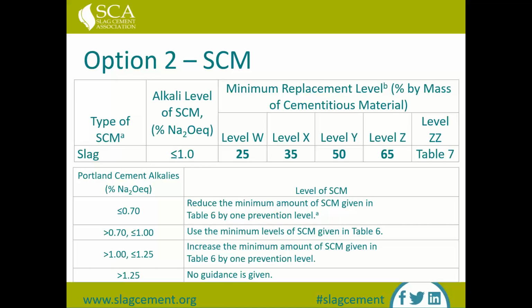What you'll want to look at is that top table there. Say if we need to meet a prevention level X, that shows 35% slag replacement. You take that, and want to compare it with the chart below it, since it may need to be altered. That 35% is based off of Portland cement alkali content that is greater than 0.7 and less than 1%. That's where you use that 35%.